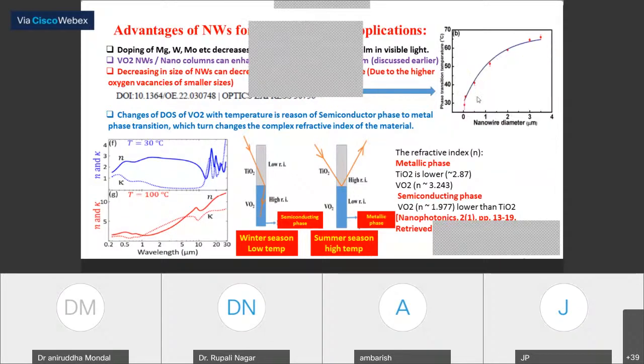If you use nanowires of vanadium oxide, which is an active medium and can change the refractive index with temperature, the nanowire dimensions will change in such a way that if we go for low dimensional nanowire structures, the phase change temperature will be decreased, which is very important. This kind of structure can be used to fabricate the smart window, as well as to coat the outside of satellites which go to the upper atmosphere, where temperature changes are very important to manage in order to protect all the electronic devices. So these phase change materials are very important, and as nanowires, they are most important to protect all the electronic devices inside the spacecraft.